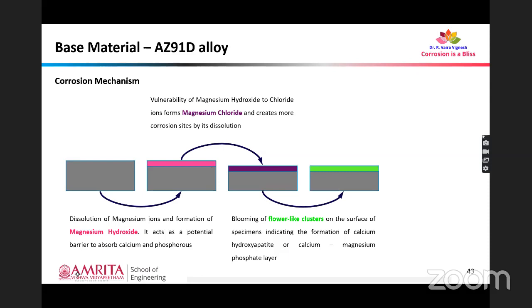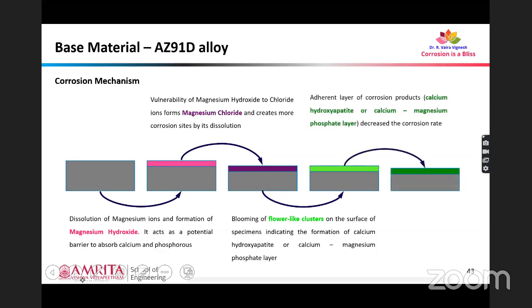And there is more accessibility of magnesium ions to phosphate ions. So that results in the formation of flower-like clusters. Those flower-like clusters are nothing but a calcium magnesium phosphate layer or calcium hydroxyapatite layer. That formation of an adherent layer of corrosion product decreases the corrosion rate in the material. So initially we had a high corrosion rate, then there is a reduction in corrosion rate. That is all because of this formation of hydroxyapatite. If there is a formation of hydroxyapatite, it is obvious that the material is biocompatible.